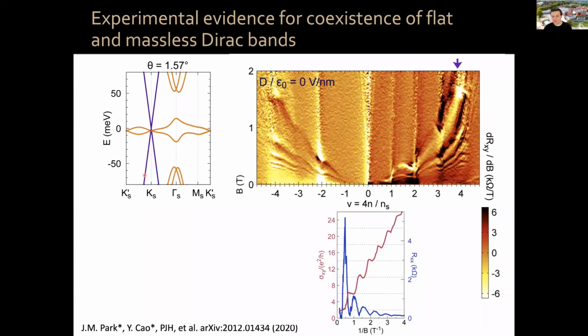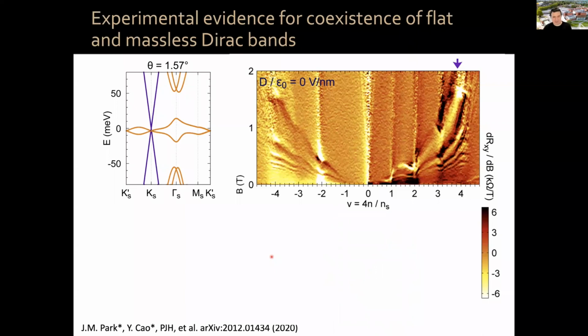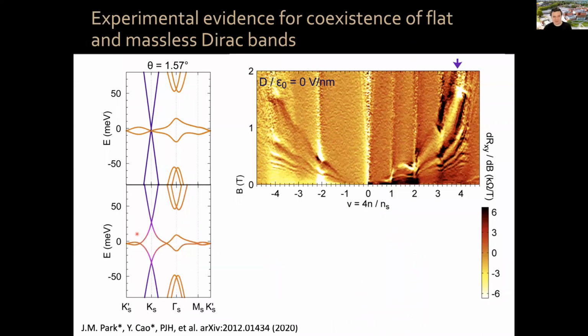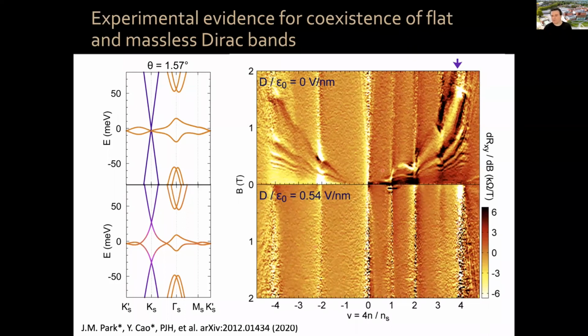In fact, if we put our chemical potential near 4 electrons per moiré unit cell, so we're here, and we cross only the monolayer-like band, and you measure the quantum Hall effect, you measure the half-integer, relativistic quantum Hall effect of monolayer graphene, okay? So we know that indeed the electrons are just monolayer-like, graphene-like. Now, if you apply a finite displacement field, okay, and you explore this region, then you get rid of that monolayer-like band, okay? And you only see these vertical features associated with the magic angle twisted bilayer-like band.